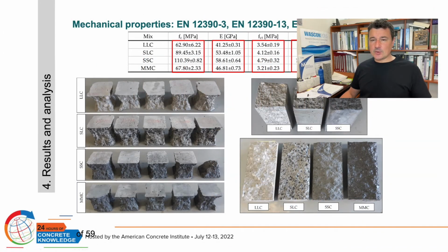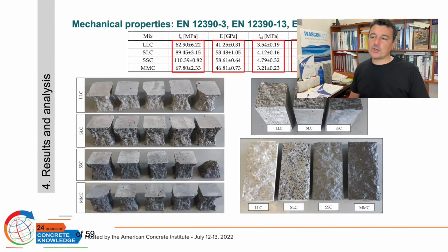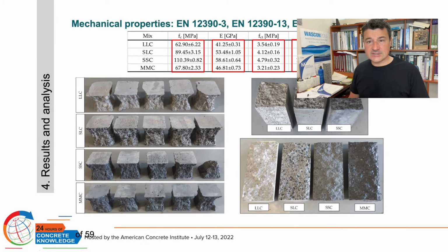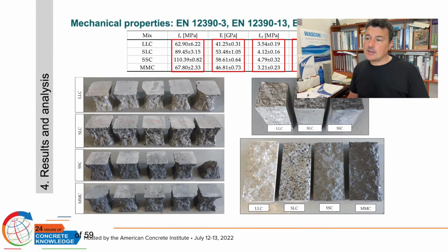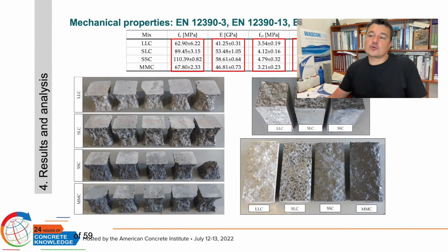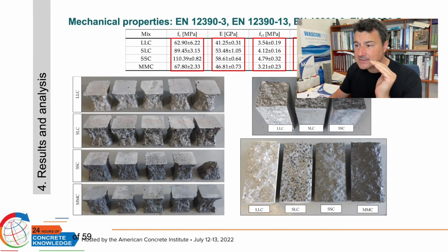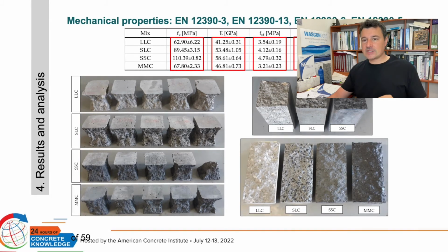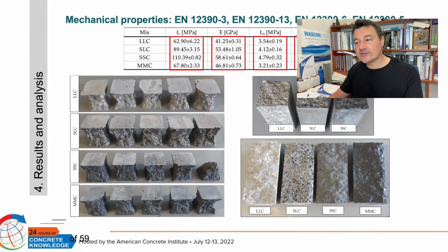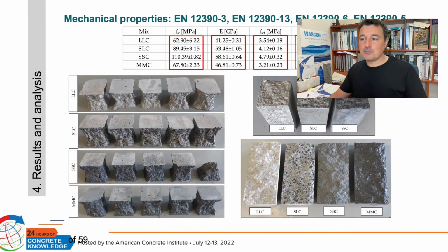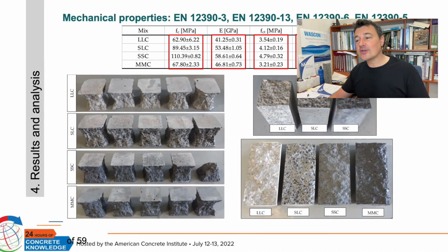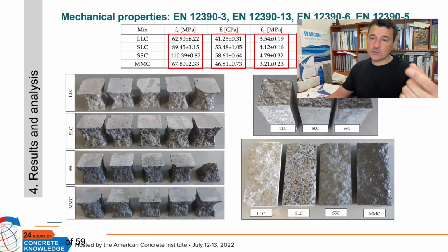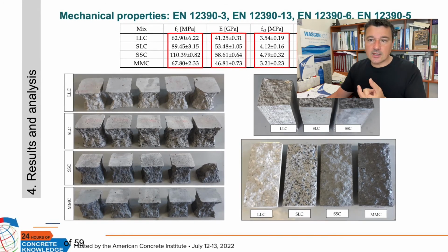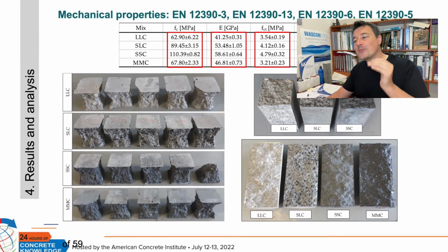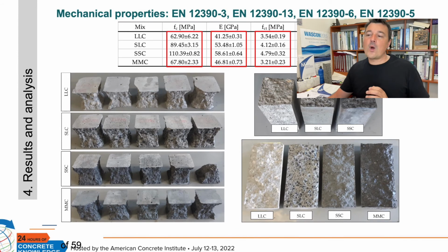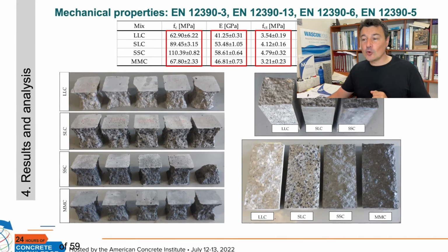What about the mechanical properties? Remember that we are using a little bit more than 300 kilos per cubic meter of cement, in this case cement type 1, Portland cement, and the compressive strength of the control concrete is very high. It's not low. It's 62 megapascals. But if we incorporate coarse siderurgical aggregate to this concrete, we can increase the compressive strength to near 90 megapascals. This is a high performance concrete. And also, if we incorporate not only the coarse siderurgical aggregate but also the crushed siderurgical sand, we can increase the compressive strength to more than 100 megapascals. This is a very good concrete.